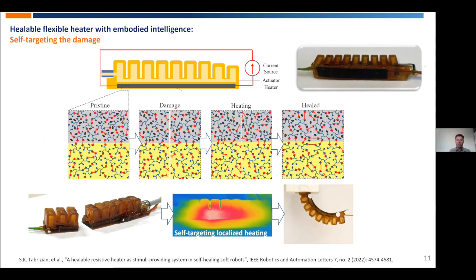So we can apply a current to heat up the heater. However, you also have a higher resistance at the location of the damage. And I think this is very interesting, as you will have a self-targeting heating and healing in this case. So if you apply a current, then the location that will be heated and healed is the location of the damage. So this is another example, I think, of an embodied intelligence.